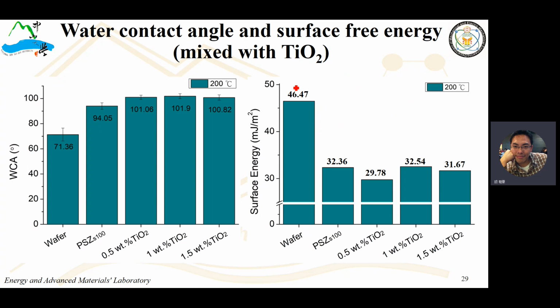And we compare the surface energy of the pre-ceramic precursor incorporating titanium dioxide. We get that when it's about 0.5 weight% of titanium content with the pre-ceramic precursor, its surface free energy is below 30. However, its contact angle is not very effectively hydrophobic compared with the other compound of the pre-ceramic precursor with fluorinated compound.